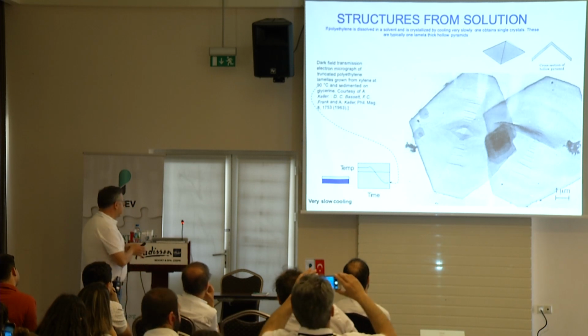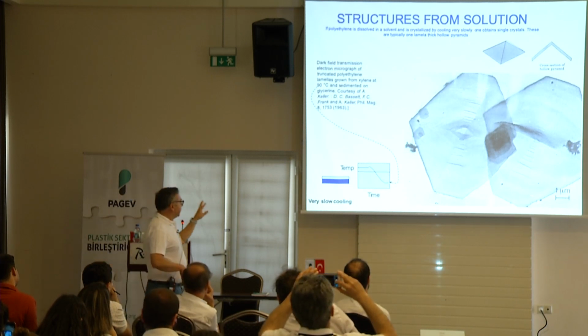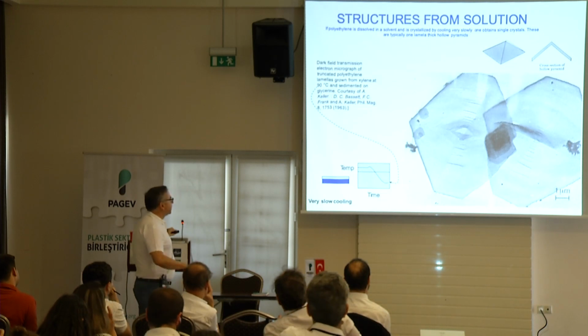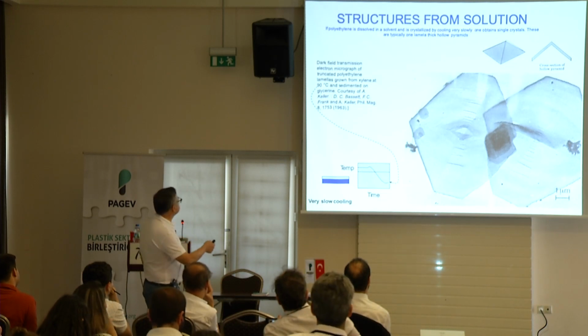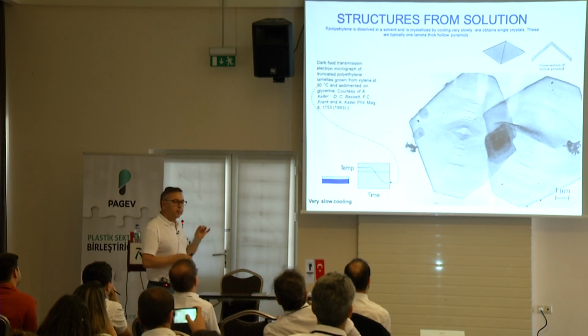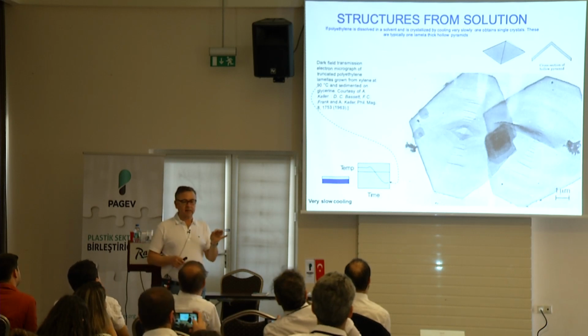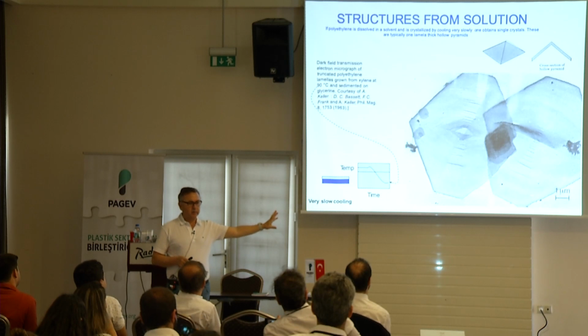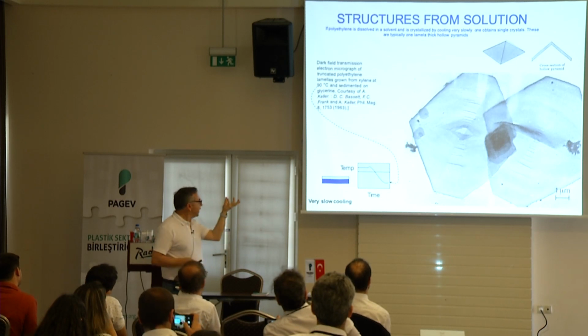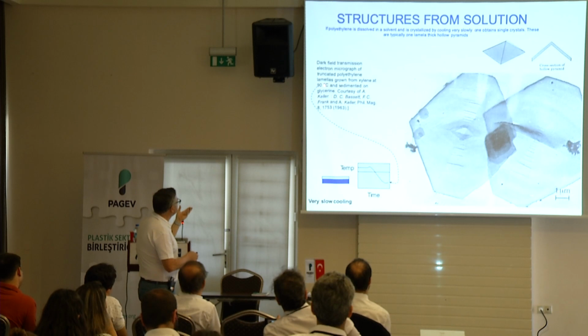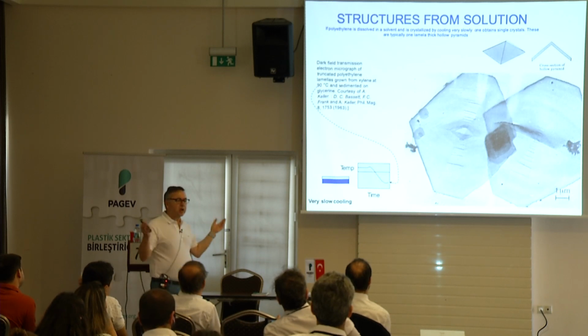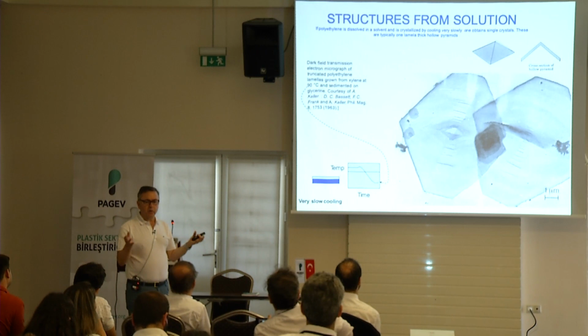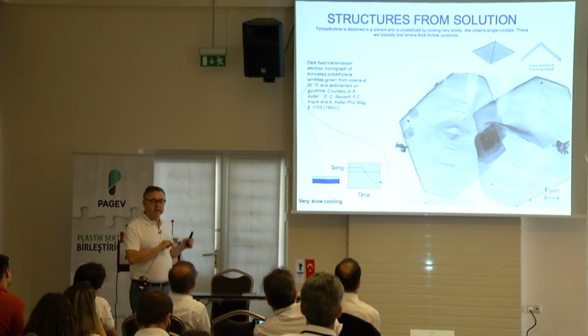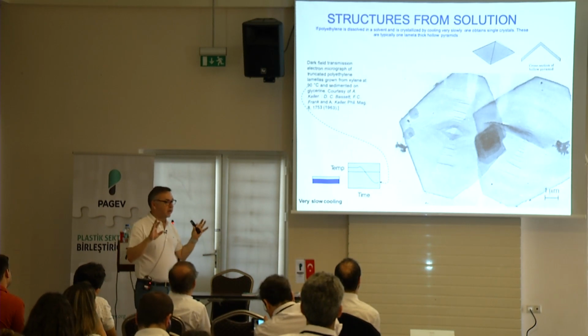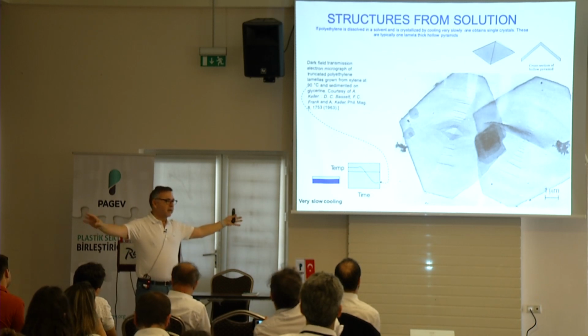So if you take an extreme situation, you take polyethylene, this is polyethylene, and you make a 0.1%, very, very dilute solution at about 120 or 90 degrees in xylene. You can dissolve it. It's basically like a xylene liquid. What you're doing in this case is that it's not a spaghetti ball anymore. They are polymer chains all by themselves in a solution. They are not touching each other.